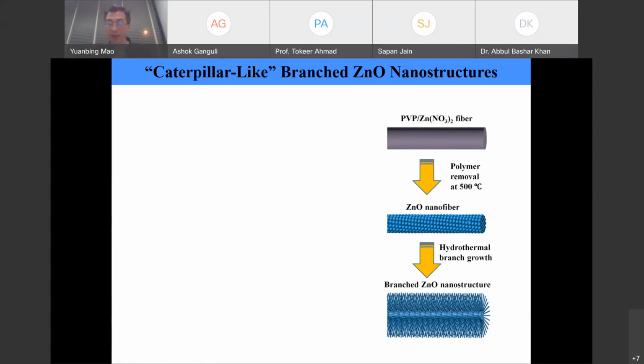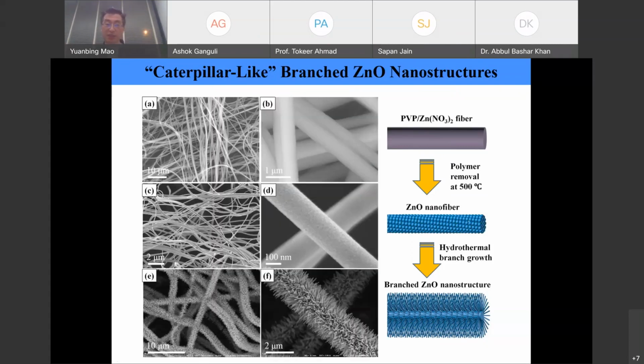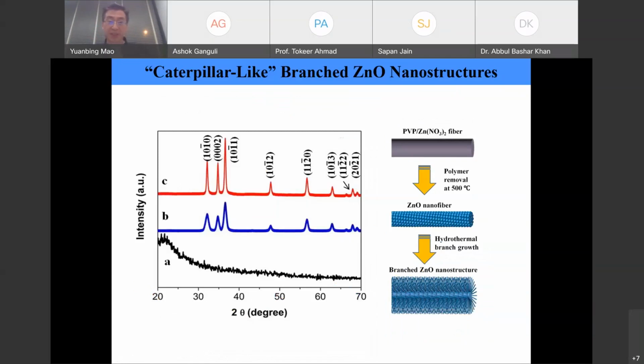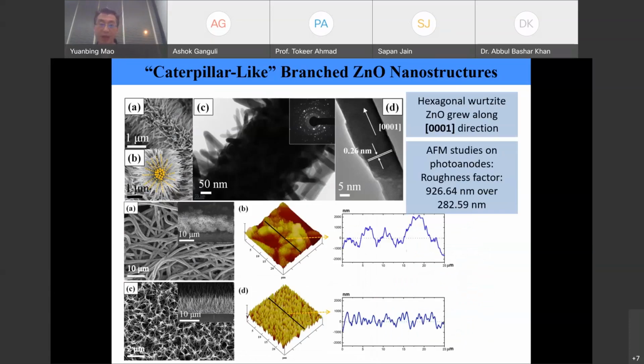And then the next step is the same as I showed you earlier: use hydrothermal synthesis to grow the branches. And that's what we did. And these are the images, and especially when the resolution is high, we can see that these nanofibers are actually composed of nanoparticles, and then we can grow the branches. I hope I'm not too slow here. Anyway, then we can confirm this in terms of the crystal structure as well, and we did more characterizations.